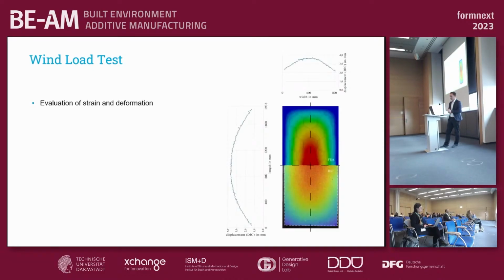And when we look into the evaluation, we compared two different systems. In the bottom part of the picture, you see the DIC picture. So that is the actual deformation of the panel during the loading. And on the top, there's a finite element simulation, which represents the physical tests quite well. And we measured at the maximum load of 4000 Pascals only 2.3 millimeters deformation.